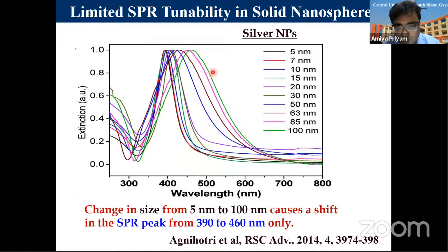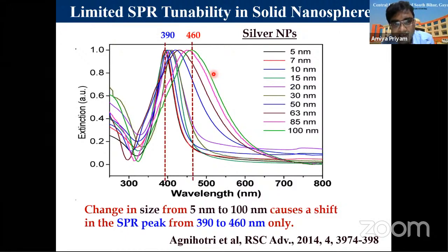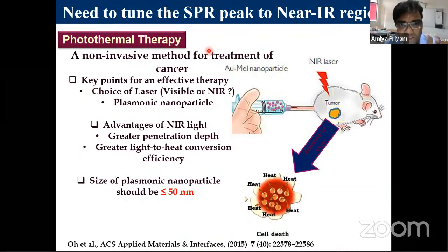I'll come to that point. Similarly, there is also limited tunability in the case of silver nanoparticles. If, keeping the shape spherical, you change the size from 5 to 100, you will have only a 390 to 460 nanometer change in the absorption peak. So why I'm saying there is a need to tune this SPR wavelength is that the SPR frequency we have just seen needs to be tuned to a desired wavelength for different types of application.